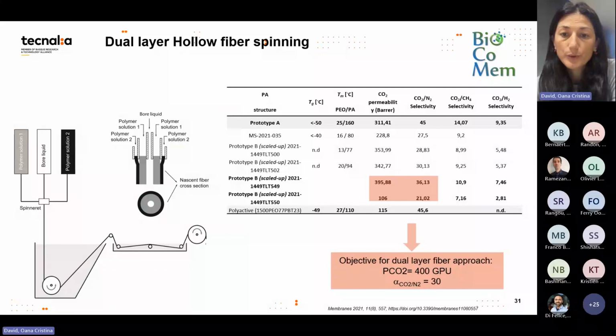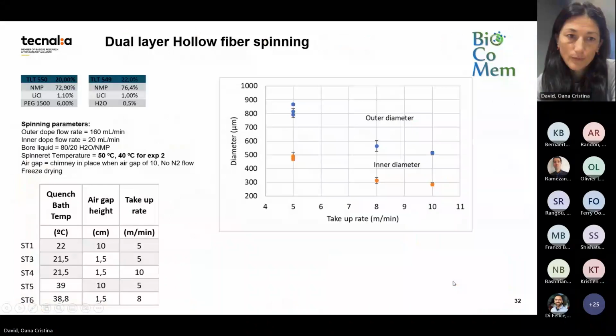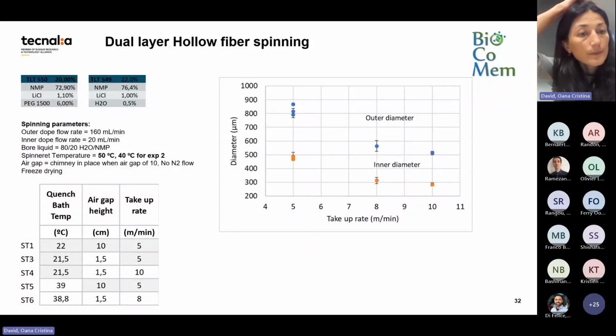dual layer hollow fiber approach, we can achieve a selective layer, a thick one, of about 1 micrometer, because if the entire layer is made with this polymer, the pore structure that can form by the NIPS process will collapse into a dense layer, but the pore structure made with 550 will stay open. So we assume values of 400 GPUs and a selectivity of carbon dioxide to nitrogen of 30 can be achieved. And then I show spinning experiments where we change a few parameters during the spinning session.